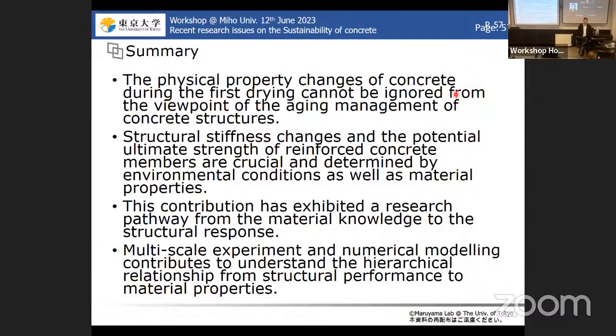Yes, please. It was a really interesting presentation, especially about the stiffness related with the shrinkage and the drying shrinkage. And my question is, in your work, did you also study the autogenous shrinkage and the stiffness? Did you find the same correlation? Because what would we find in a high performance concrete, for example, where the autogenous shrinkage is usually higher than in normal strength concrete? What would we expect? Even more influence about the shrinkage? Because at the end, autogenous shrinkage is also due to internal drying, to the reaction of the water. So what would we expect in regard to the stiffness?